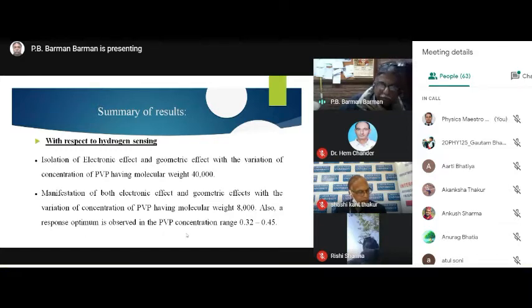A response optimum is also observed with PVP in the range of 0.32 to 0.45, but as I told earlier, 0.32 or 32% of PVP gives the better result.